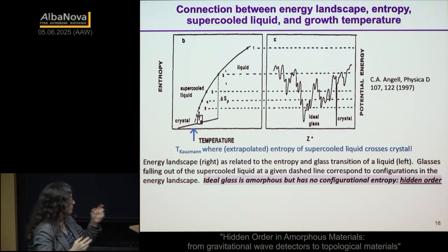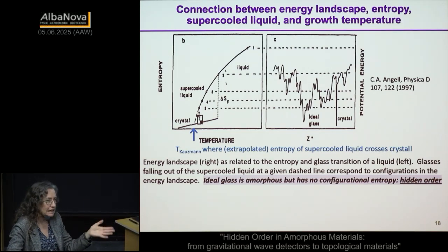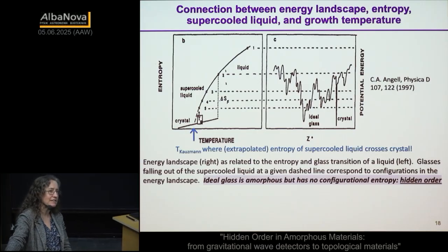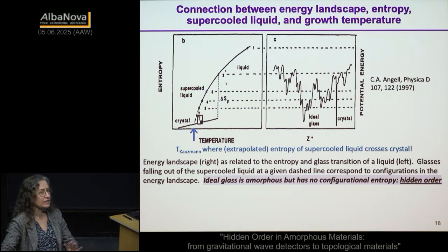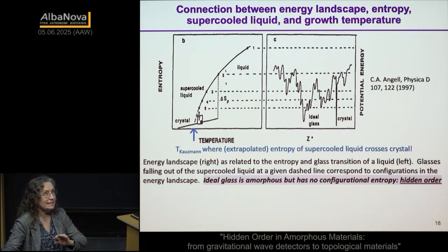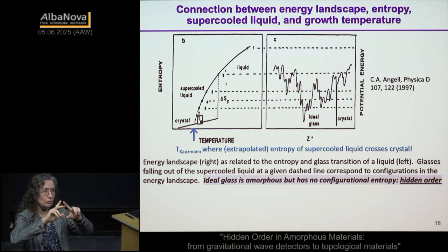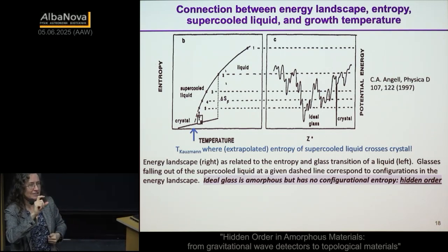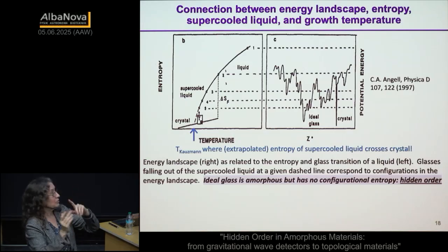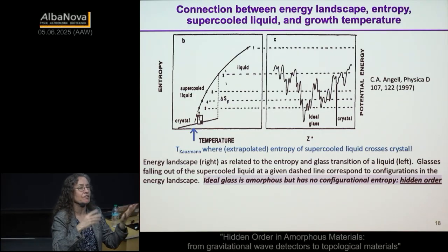And in terms of my arguments, the Kauzmann temperature, in fact, this is known, the Kauzmann temperature for silica is very low. And you actually get the Kauzmann temperature from looking at the heat capacity of the liquid state. So it's not at all to do with a solid. You get the Kauzmann temperature out of the heat capacity of the supercooled liquid. And silica ends up having almost all of its enthalpy already gone by the time it hits the glass transition. So the glass transition in silica has a tiny signature in the heat capacity, really tiny. The way you get the Kauzmann temperature here is an extrapolation, but you can plot this in enthalpy space instead, which is another way of looking at it.